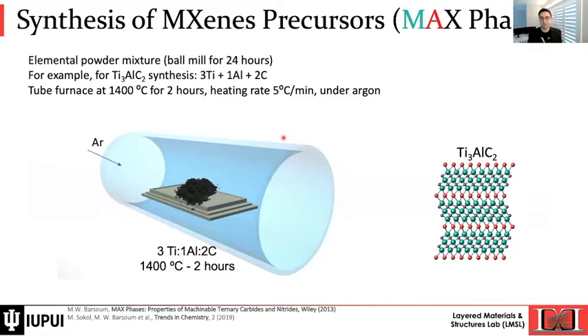To synthesize these precursors, I'm going to focus on Ti3AlC2, the precursor of the well-known MXene Ti3C2Tx. To synthesize Ti3AlC2, all we need to do is combine the required molar ratio, meaning the stoichiometric ratio of 3 titanium, 1 aluminum, and 2 carbon, of just elemental powders that you can buy from any chemical company. Then you mix it and put it into a furnace under a controlled environment, meaning inert gas at atmospheric pressure, and take it to a high temperature where this phase is known to be thermodynamically stable, and hold it. For example, for this phase it is 1400 degrees, 2 hours, and by doing that, you get this structure by reactive sintering of the 3 elements.